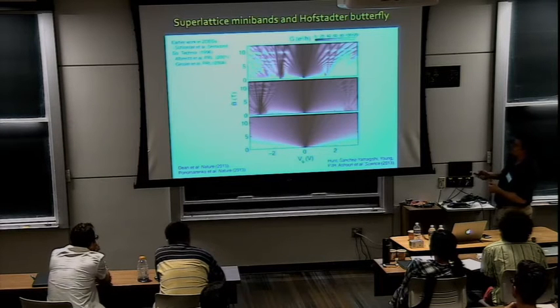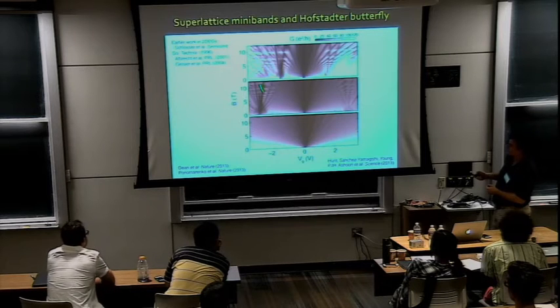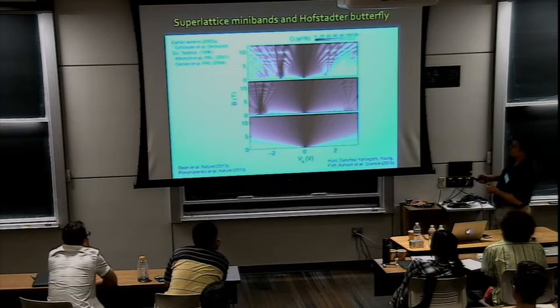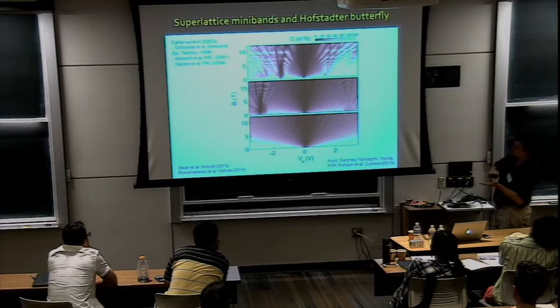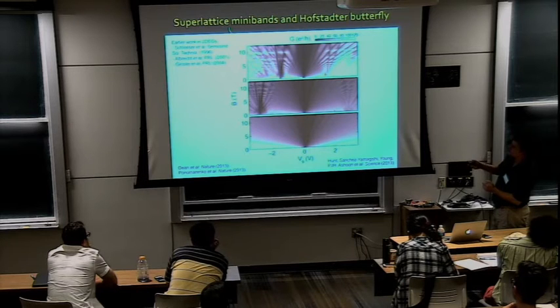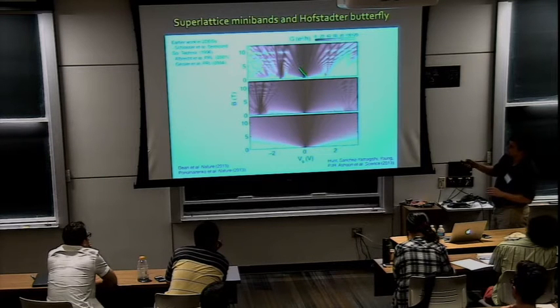But if you now measure the conductance of these devices as a function of magnetic field and density, okay, here is what regular graphene looks like. You just have a fan diagram. For graphene on hBN with a small twist angle, you have this intersection of fan diagrams, okay? And this actually is a reflection of the Hofstadter butterfly spectrum, the values at which this intersection of lines appears.